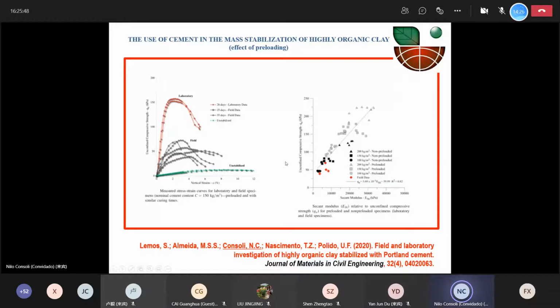We also measured the secant modulus of these specimens, and we have done a correlation between unconfined compressive strength and the secant modulus. We have the results from the lab, and the red ones that we have here in the bottom are the ones that we have collected from the field data. And so at least they fit the exact same curve, but as I said, the mixture gets them quite below here. This is a problem of execution.